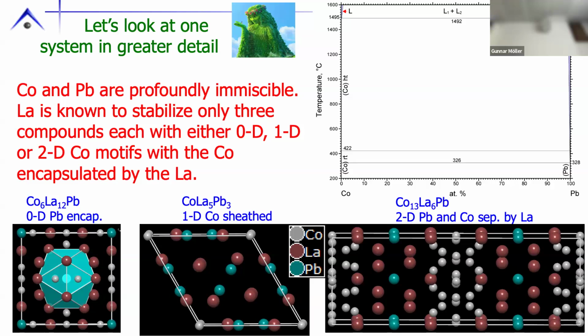And I would love it because for me, what's remarkable, I always thought crystals had their own rules. You know, the bonding settled old scores and arguments, but in intermetallics, which have more flexible bonding rules, you can find some oxides with very rigid bonding angles that you can make and violate this antagonistic pair rule. But intermetallics, it holds every time I find a new material, and I'll keep going on it. But immiscibility is not well understood yet. And I would love it if it was.